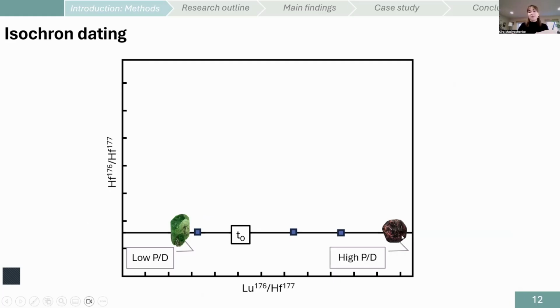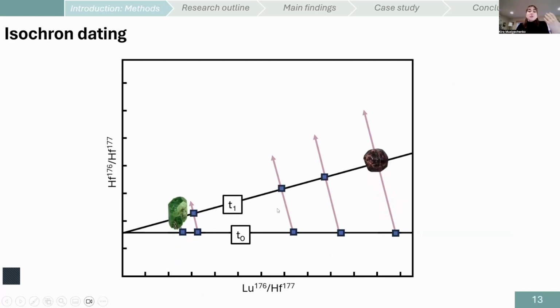As the time passes, some of that lutetium in all of the minerals starts decaying to form hafnium. The ones that have more lutetium are going to form more radiogenic hafnium, so the position of these points is going to change more than the position of those points. Now, that brings us to some intermediate time T1 in the middle of it. What we see is that if we plot the isotope composition of all of the minerals again, if the system remained closed and everything remained in equilibrium, they're going to plot again on the same line. That is our isochron. At this stage, the slope is still very shallow, reflecting the short amount of time between T0 and T1. Let's move forward in time again.